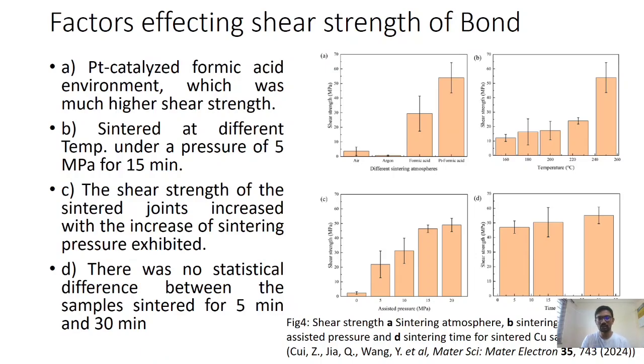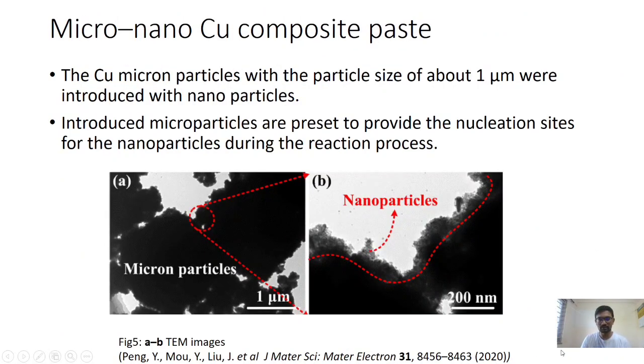Now we will discuss when we use microparticles plus nanoparticles copper composite paste for bonding copper-copper. In this we have used microparticles. You can see this black part is microparticles, and we have sprinkled nanoparticles on them. At the time of reactions, these microparticles are nucleating sites for nanoparticles. You can see that these nanoparticles are growing at the time of reactions, and after that both get mixed, nanoparticles and microparticles.